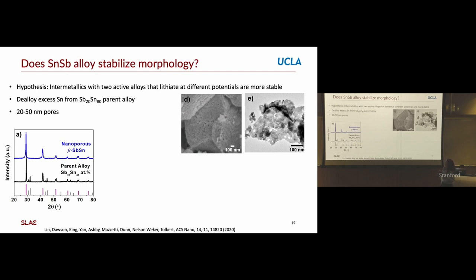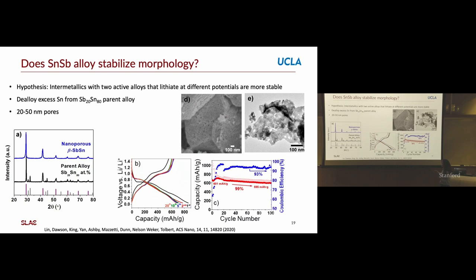And so the hypothesis was this intermetallic of tin and antimony is going to be more stable than just the tin by itself. And so again, we took a tin antimony alloy where we had a lot more tin and we etched out the excess tin. And so we got an alloy that was equal parts tin and antimony with nanopores. These pores are a little smaller for better or worse, but sometimes you can't really control the size of the pores with this material. But we do have cycling data, and we found that it cycles very well, this tin antimony alloy. And so we wanted to put it onto the beamline as well and see what imaging would tell us.